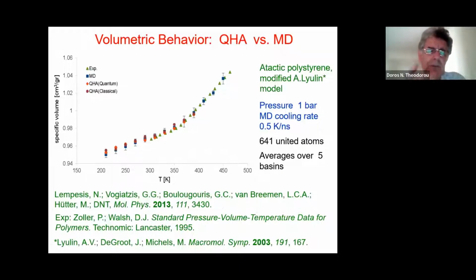Using this quasi-harmonic approximation within the basins in polystyrene glass, based on 5 basins, not very many as we see here, we can accumulate, for example, the specific volume as a function of temperature. And here I show you these results. The force field is based on a previous work by Alexei Lyulin. Essentially, we impose a pressure of 1 atmosphere on all sides at each temperature on the box, and then we let the box go to the configuration that would correspond to the minimum of the free energy with respect to the dimensions of the box. And that volume, the volume we plot as a function of temperature.